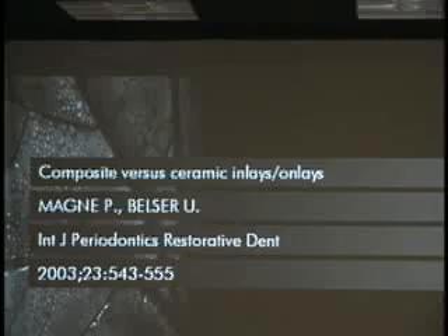We studied a little bit of that with finite element in a 2D model, comparing inlays and onlays and the different materials, and I can tell you, not much difference. What is really different is an inlay versus an onlay. And that was really interesting because an inlay restoration actually gives a lot of bad stresses at the interface of the restoration. This is the stress at the interfacial bond. And inlays actually have lots of tensile stress. You see the zero line is here. Everything that is up there is tensile stress. Lots of tensile stresses on the bond.